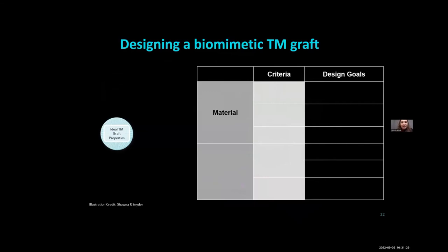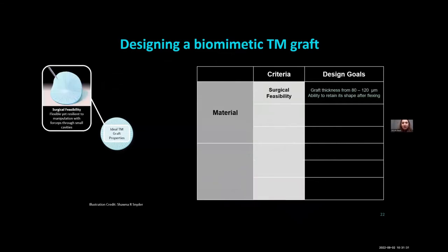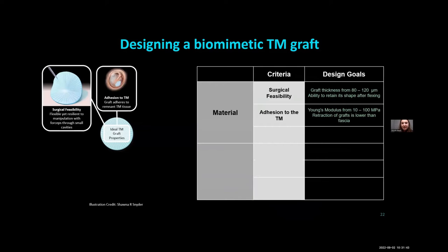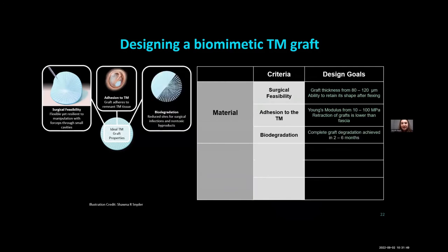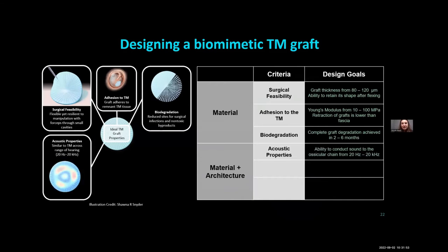So when we were looking at the TM graft, for surgical feasibility, we wanted this graft to be around the same thickness as the eardrum, starting at about 80 microns, and be able to withstand a bunch of flexing as it's placed through the ear canal. We wanted a Young's modulus in the range of the normal eardrum, about 10 to 100 megapascals. And we wanted this graft to start to degrade in about 2 to 6 months.